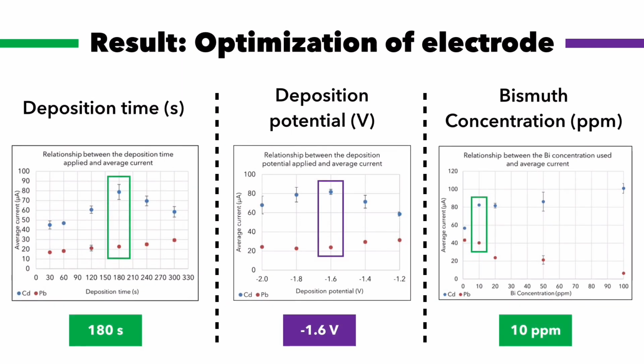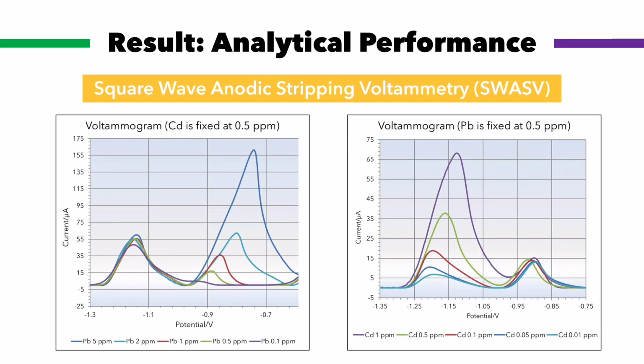This electrochemical measuring method also includes an optimization process, in which the most satisfying and acceptable conditions are a deposition time of 180 seconds, a deposition potential of negative 1.6 volts, with 10 ppm bismuth solution. Moreover, there were the results from the analytical performance process, which was evaluated with square wave anodic stripping voltammetry technique. Concentration of cadmium and lead were varied in order to use in the further step.